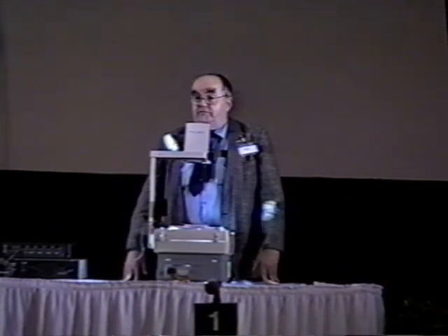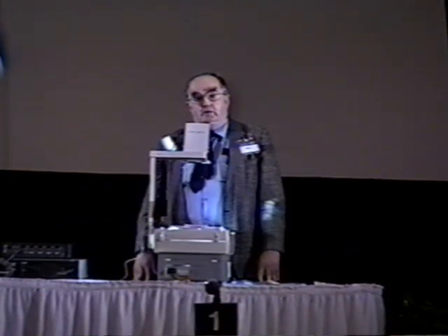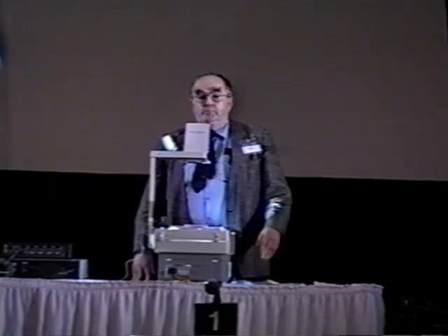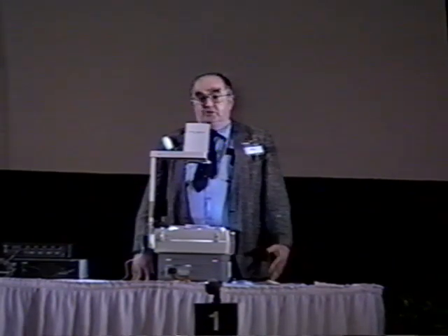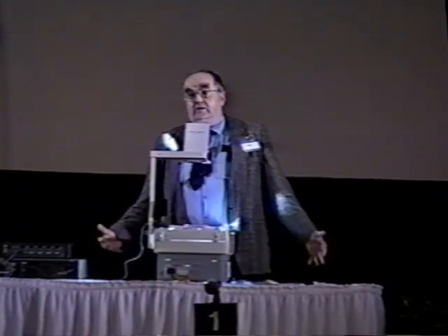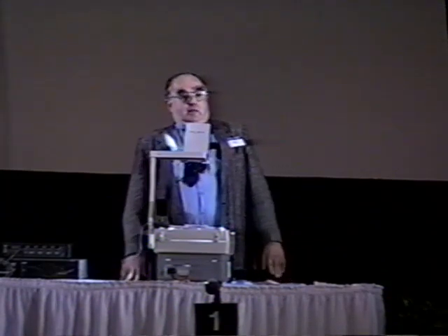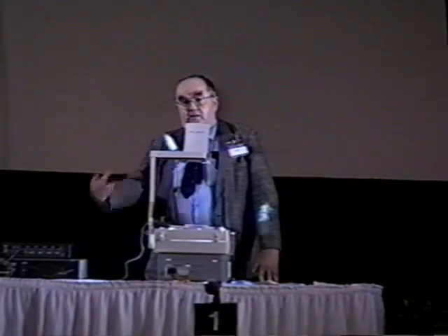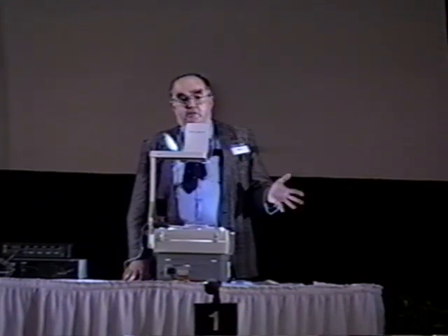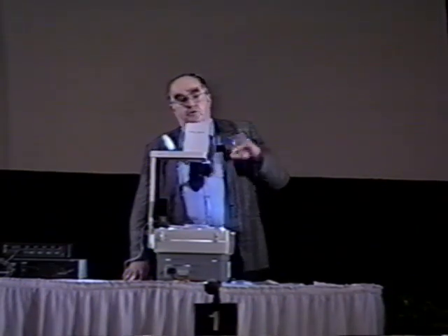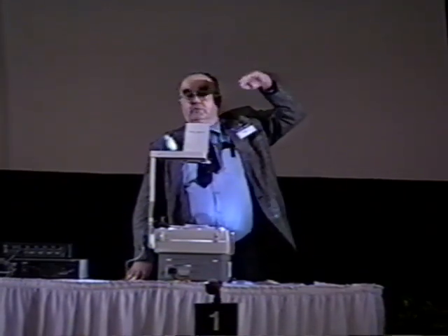Anyway, I would heat it up, and finally found that it had to be heated to at least about 150 centigrade to get anything to happen. Later, I found out that if I went much over 250, it died. The catalyst was killed. And I found out very much later that the reason for that is that the catalyst becomes sintered. Platinum and palladium, believe it or not, sinter at 250 centigrade. Anyway, the typical run that I finally zeroed in on is I would heat the hydrogen up to about 175 centigrade, wait an hour or two, and the temperature would go up and then level out, form some sort of asymptote.